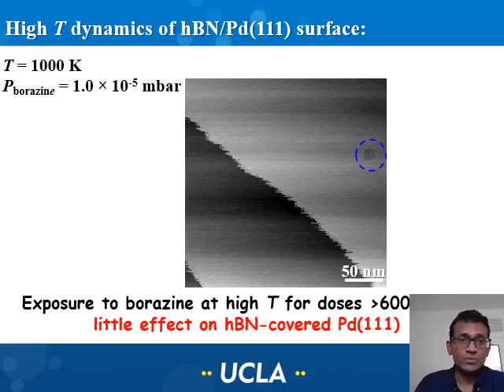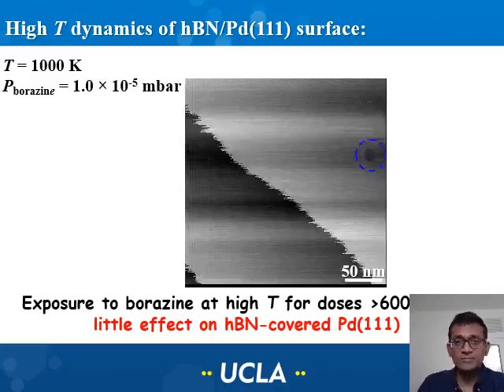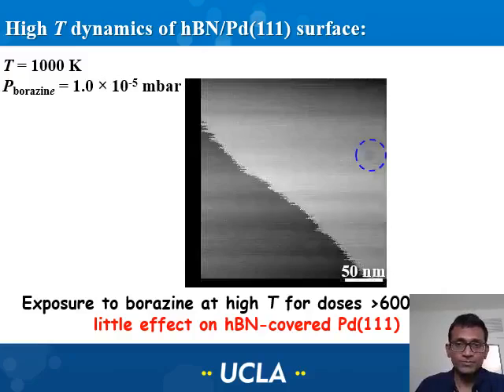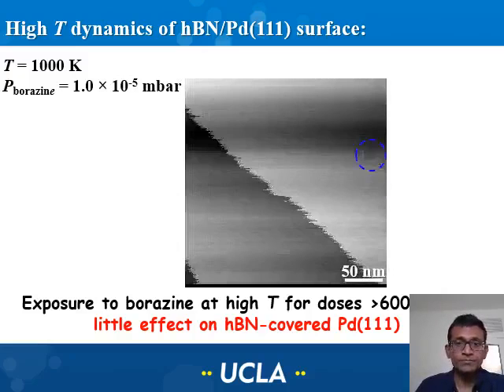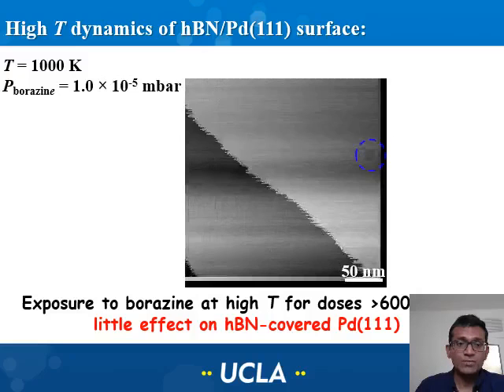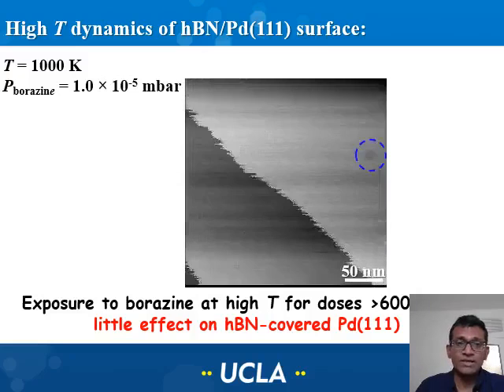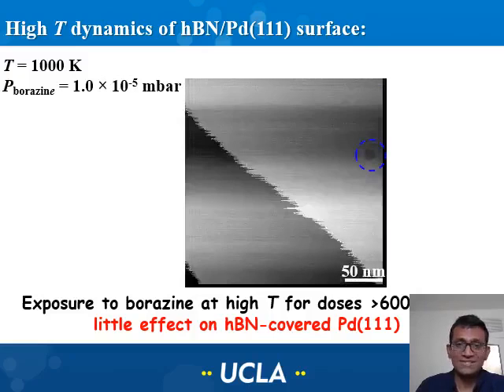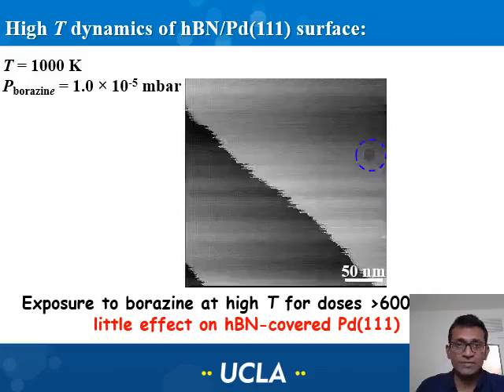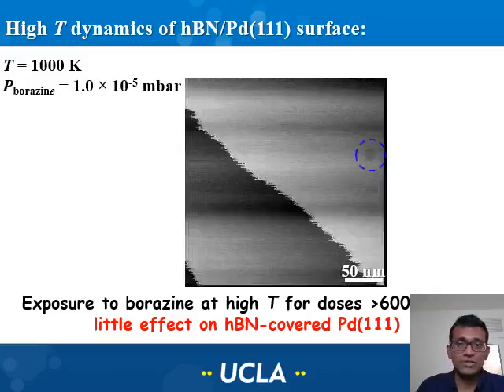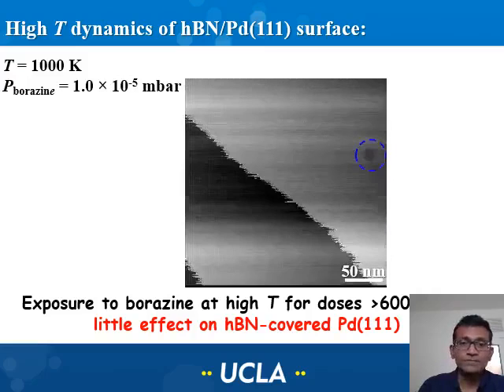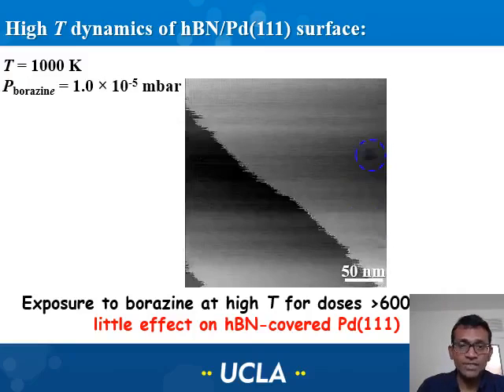This is an experiment where we are annealing the sample at 1000 Kelvin, and we are maintaining a positive pressure of borazine. This is a time-lapse scanning tunneling microscopy movie, or images acquired from the same field of view. In this particular experiment, we exposed borazine at this high temperature for doses over 6,000 langmuirs, and we did not observe any deposition of hexagonal boron nitride on these surfaces. And in these movies, you probably have seen some small